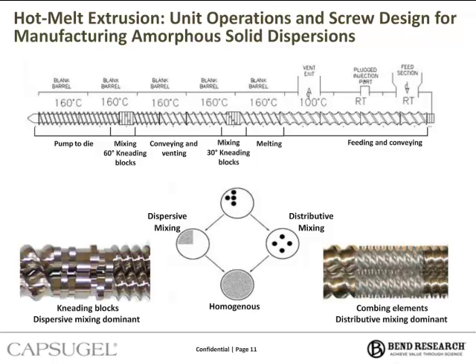And now the next unit operation is conveying and melting, and this occurs after the feed zone. Now the primary purpose here is to move powder away from the feeds, and energy is introduced via heat transfer from the blocks and shear. And this is dependent on the melt point of the components as well as the particle size of the components. So the third unit operation is mixing. And here our goal is a well-mixed material at the molecular level, which creates a single phase.